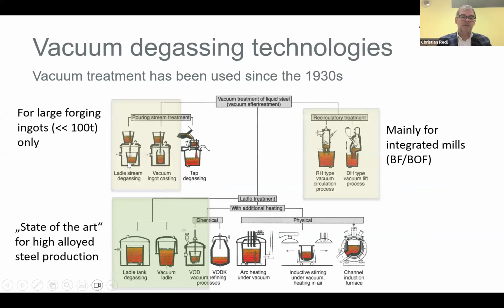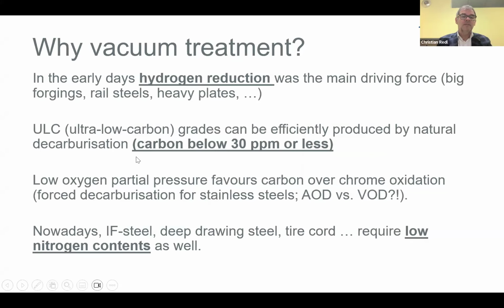And of course, the low oxygen partial pressure under vacuum favors the carbon oxidation over the chrome oxidation, which is very important if you are going to produce stainless steel or very high alloyed steel with a very high chromium content. The reason is simply that if you are blowing oxygen to reduce the carbon under atmospheric conditions, you will oxidize a lot of chromium, which you add as an alloying element.